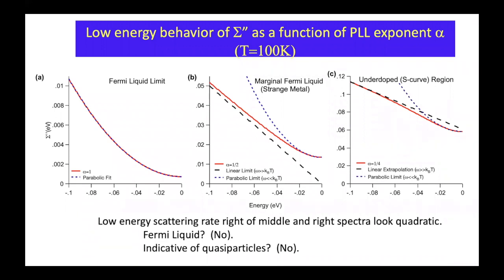So the first thing we looked at is to symmetrize the scattering rates, not the electron structure, not the band dispersion. So we can symmetrize the self-energies. Sigma double prime should be even and sigma prime should be odd. And then put in some canting, one side versus the other, and look at a variety of possible cantings with basically similar form on both sides. We find we get the best results if it's symmetric. But this is all uncharted territory, so it is true that we don't have full control of the unoccupied side. But to zeroth order, we find the best result if they're symmetric, and they're quite good.